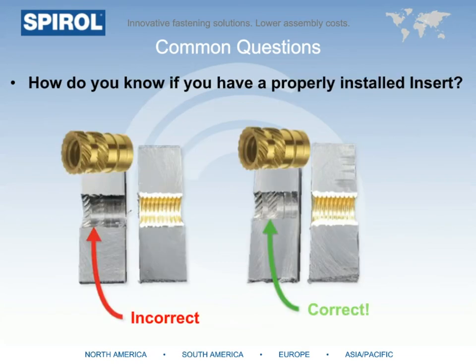So how do you know if you have a properly installed insert? This is most definitely a destructive test and maybe even a little barbaric. We would literally take a hacksaw and section the plastic component with the installed insert, section it in half, then pop the sectioned insert out of the hole and ensure that the features of the insert are mirrored in the plastic as shown in the image on the right. It's extremely important to ensure proper plastic flow into the features of the insert, as this dictates the torque and pull-out performance. As you can see on the left, the plastic did not sufficiently flow into the retention features, which will result in low insert performance.